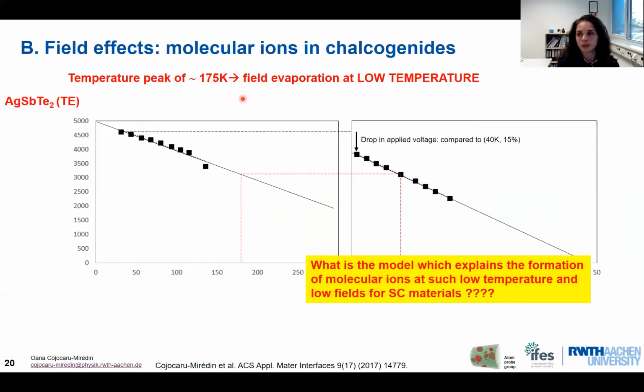So another important aspect for chalcogenide material is that the field is not that high. It's typically half of the field applied for metal. So we cannot really say that the field was so high that we have promoted the formation of molecular ions. And if the field were so high, of course, we would also have the dissociation of these molecular ions during the evaporation path.